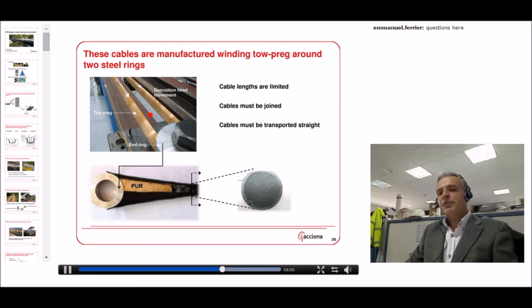The carbon fiber cables we use are manufactured in this way. You fix 2 steel rings at a relative distance equal to the final length of the cable, and you start winding tow around these steel rings. So you have a machine that takes tow and goes around these 2 rings, this way.